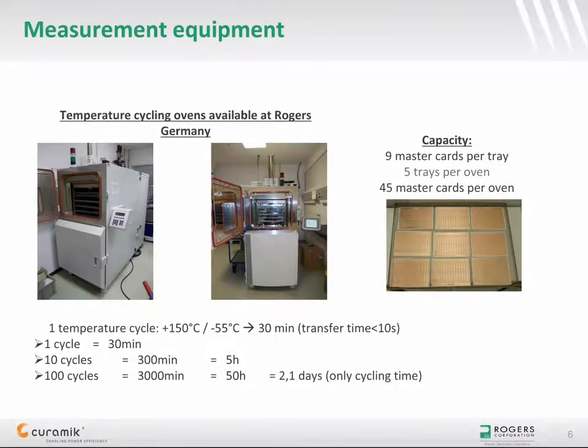Temperature cycling ovens are available at Rogers, Germany, and we perform such cycling tests for internal purposes like process control or evaluation and qualification of new suppliers and new materials. On request, we can also conduct such cycling tests on behalf of our customers. Even though this is an accelerated test method, one cycle takes 30 minutes, and depending on the number of cycles and end of life of the device under test, these tests can last for many days.